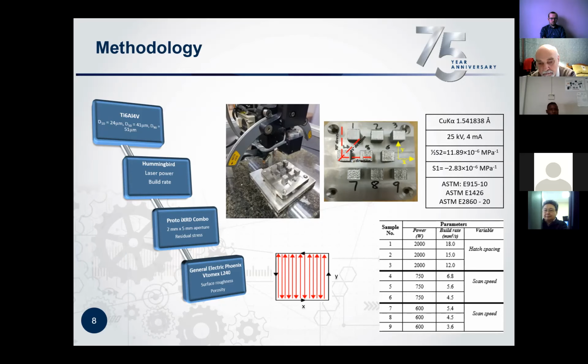We used XRD, a common method, to measure the residual stresses on the surface. These are just some of the parameters that we used and the constants that we applied when we were doing the measurements. You'll see that in terms of laser power, we varied the laser power from 2000 down to 600. These parameters actually stem from another experiment where we started by developing the process to identify a parameter window which gives us the least porous samples. So we identified these as parameters of interest for further investigation.